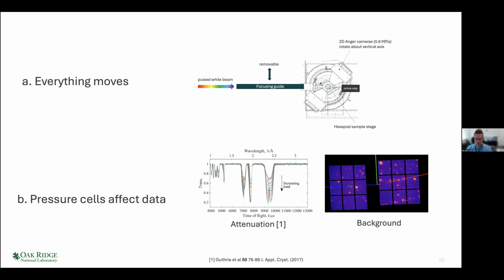The other thing which I spent a lot of time worrying about is that the pressure cells themselves affect the data. And this plot here shows the transmission as a function of wavelength shown on the top axis of a neutron beam traveling through a diamond anvil cell. And you can see there are these specific wavelengths where you get a massive attenuation of the transmitted beam. And that, of course, reduces the number of neutrons at that wavelength that then Bragg scatter from your sample. And again, this would be relatively simple if you were doing a fixed wavelength measurement. You could just choose a wavelength here where nothing is changing. But the whole goal with time of flight is to try and exploit all of these wavelengths. So this was something that had to be considered.